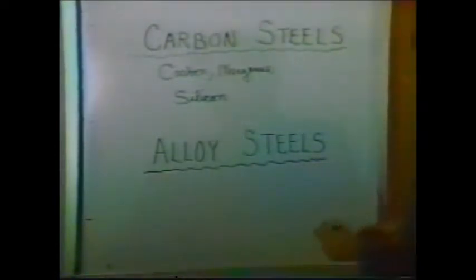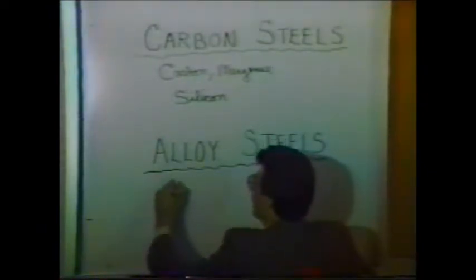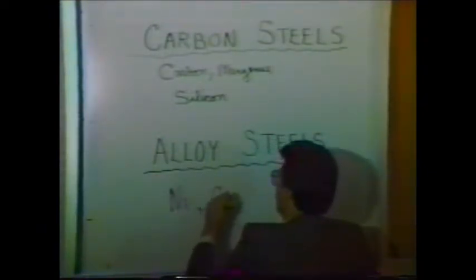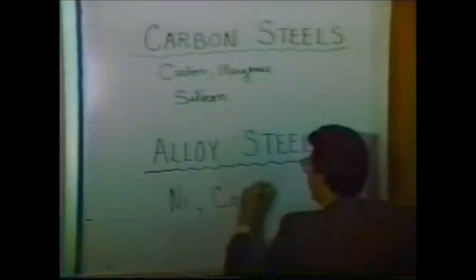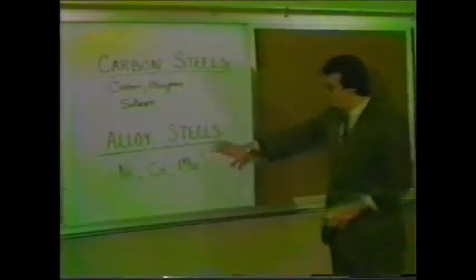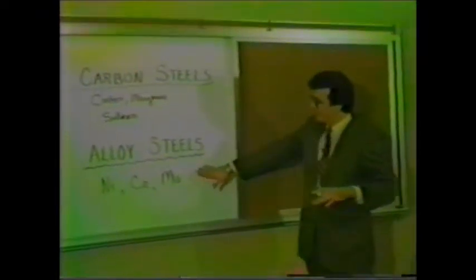Now let's contrast carbon steels with alloy steels. Again, alloy steels have as one of the basic elements in there carbon, but generally the alloy steels have combinations of either nickel, chromium, or molybdenum. And I'll just use the chemical symbols for them: nickel, chrome, or moly as it's called in the trade. Now, what distinguishes these from the carbon steels is that someone would purchase specific additions of these three elements, and the reason someone would buy these in an alloy steel is that there is a desired response to heat treatment.